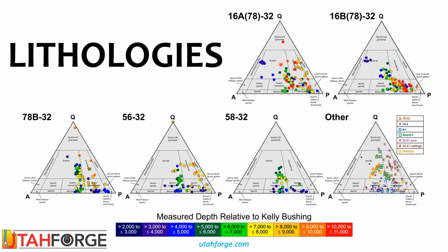Similar compositions are also observed in some wells drilled to the east of the Forge site in and around Roosevelt Hot Springs hydrothermal system. Interestingly, this compositional shift with depth is not observed in 16B, which is only about 300 feet vertically above 16A. I guess the takeaway here is that there's a lot of variability in the flavor of granitoid we're hitting in the reservoir.